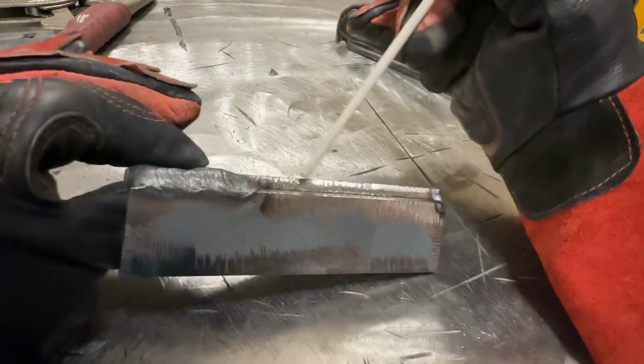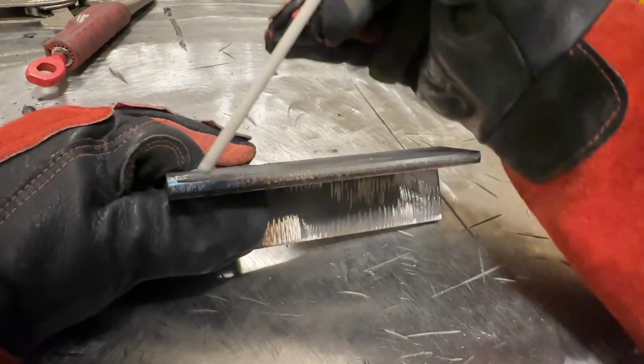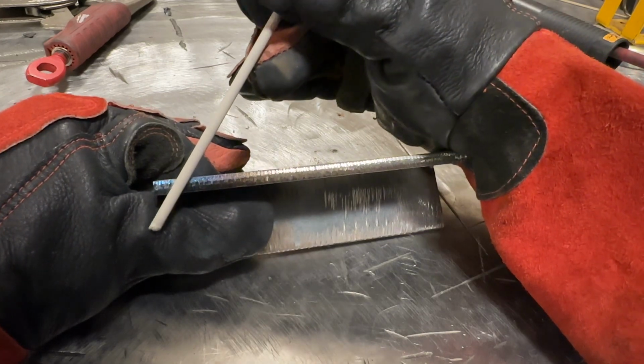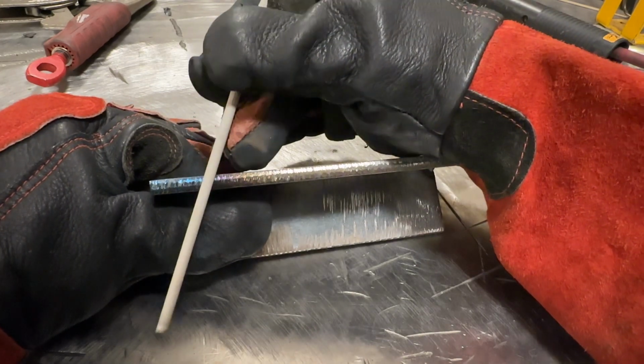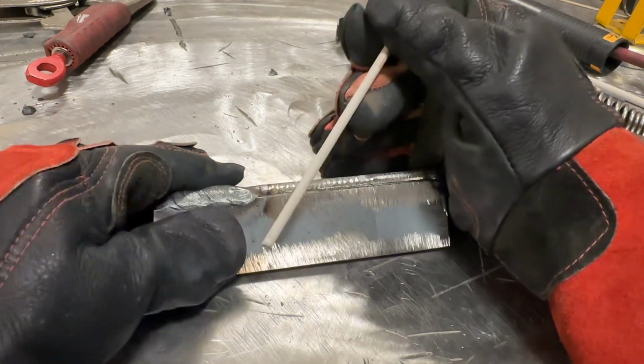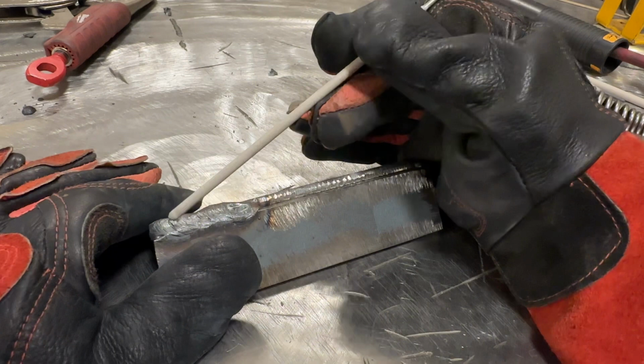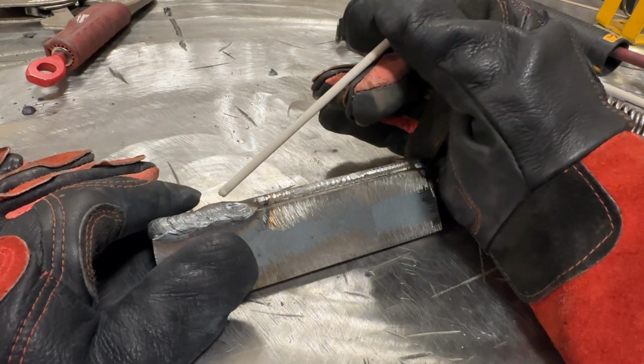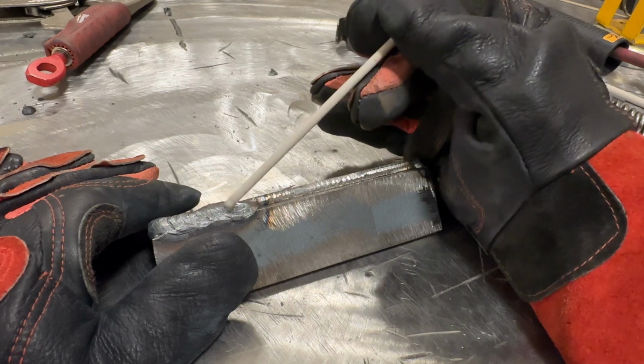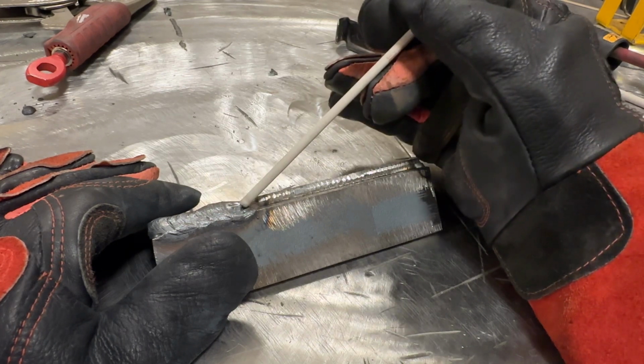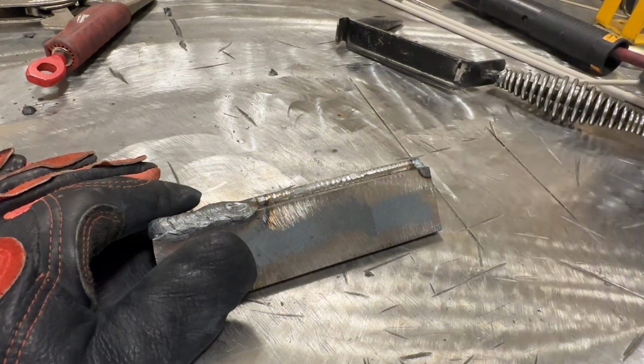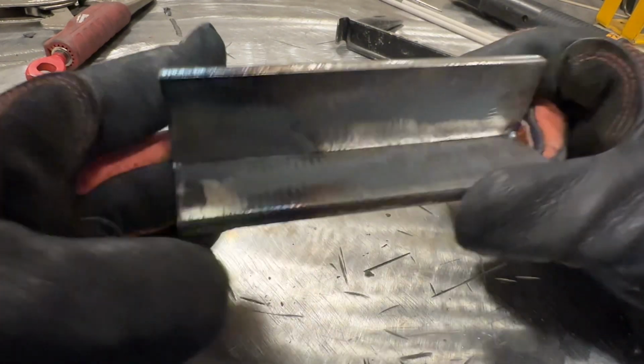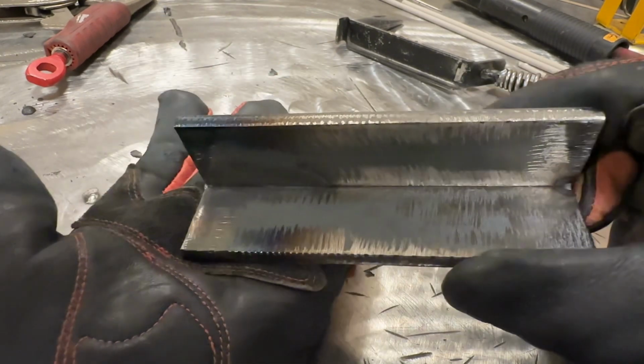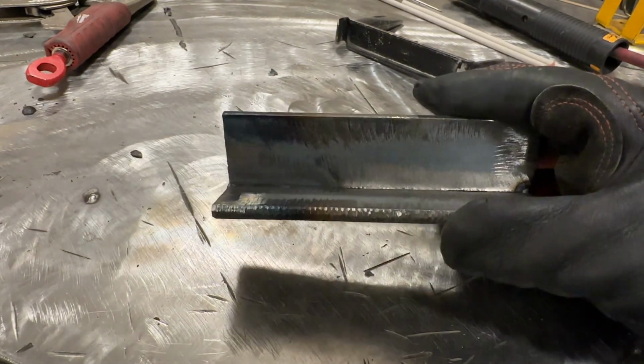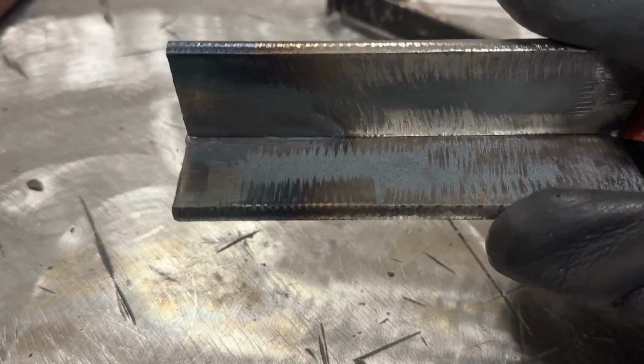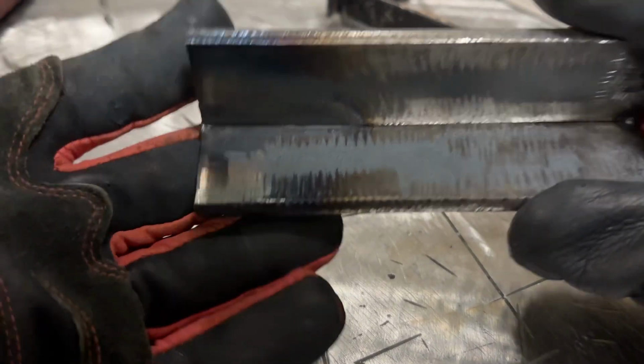Well, when you need to deposit, you can see the amount of metal that I put in. I'm more or less going like this and barely moving forward while burning off a ton of rod. And not only is that going to promote arc blow and issues with controlling your molten puddle, because your molten puddle is a lot bigger than it should be, at least in depth, you can also run into penetration problems. Now, I didn't really expect to see any penetration in here anyways, but just looking at that, and let me zoom in slightly here, that's a little bit higher detail for you, sorry about that.